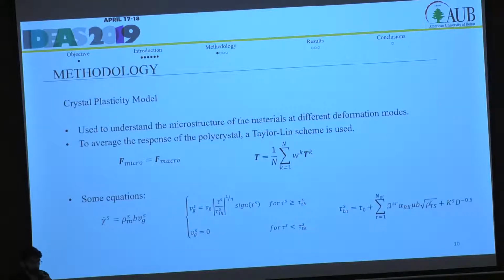So in order to proceed with our modeling, we use the crystal plasticity model, since it captures large and severe plastic deformation. And this crystal plasticity model is coupled with continuum dislocation dynamics to capture the dislocation density evolution within the crystals. Also, in order to average the response, a Taylor-Lin scheme is used to average the stresses inside each crystal, and it's also assumed by Taylor that the deformation gradient at the micro scale associated with each grain is equal to the macroscopic deformation gradient. And here we have some constitutive equations.